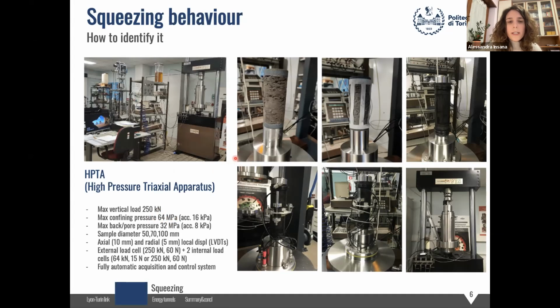It is fully controlled with automatic acquisition of data and also local measurements of strains in the radial and axial direction. So you see on the right some pictures during the setup of the specimen. This actually is a specimen of clay shales coming from central Italy. We have just concluded an experimental campaign on such material.